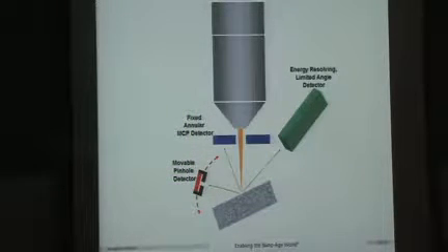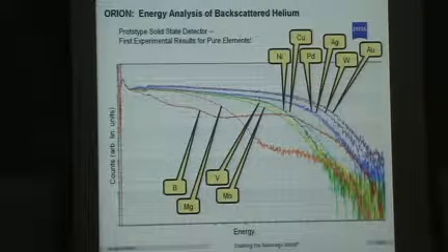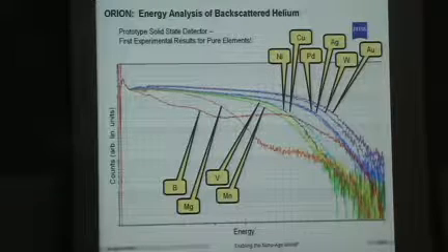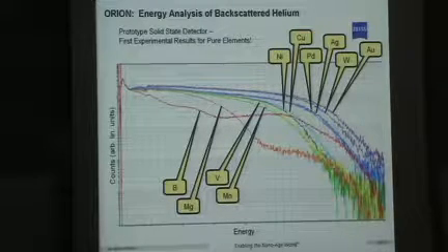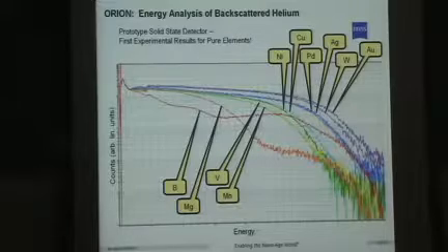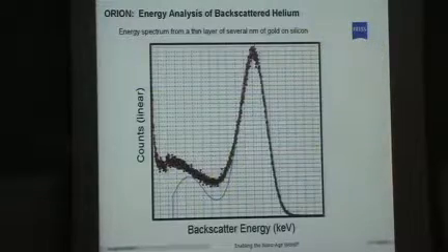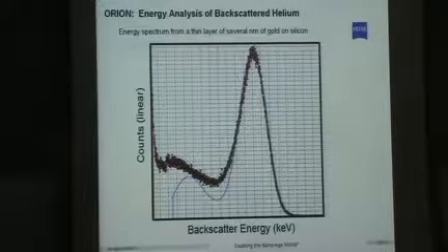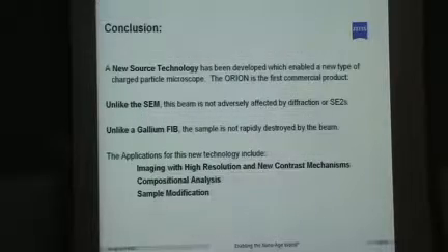This is a cartoon diagram of our backscatter detector, and that is now an option with the instrument. We've developed a solid-state backscatter option. And these are the different spectra you get with different bulk materials. And you can see they are easily discernible. Even copper and nickel, neighbors on the periodic table, are easily discernible. Here's a thin film that we were able to analyze, and we were actually able to do angstrom level thickness monitoring using that technique.